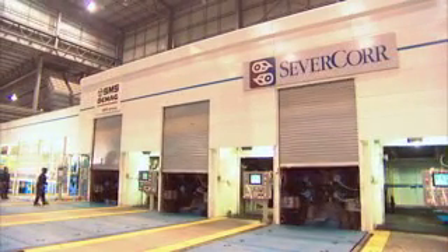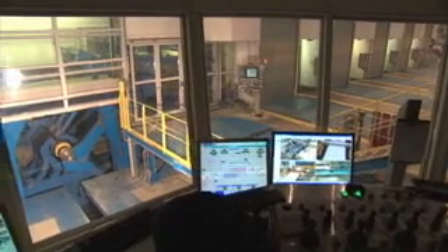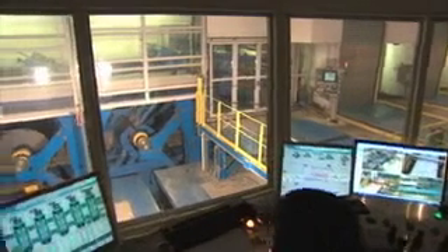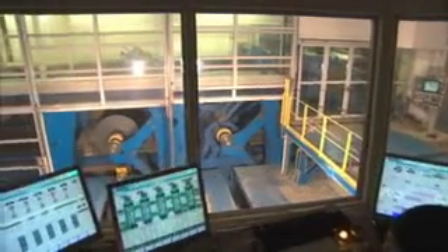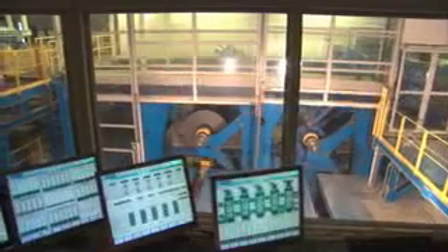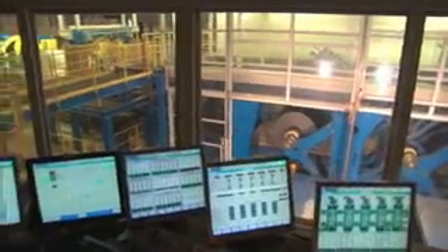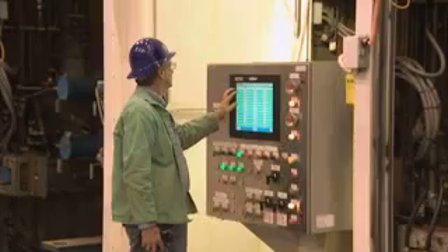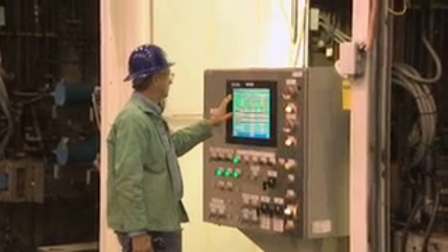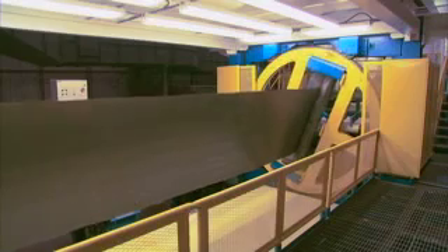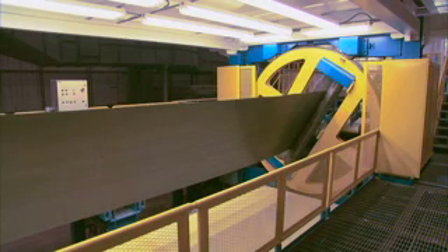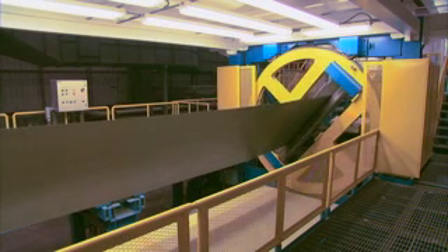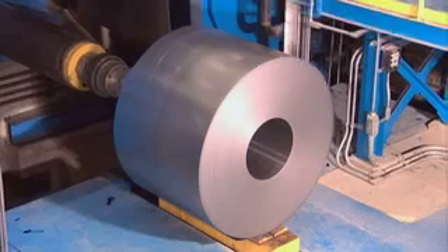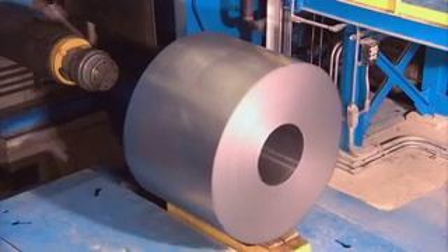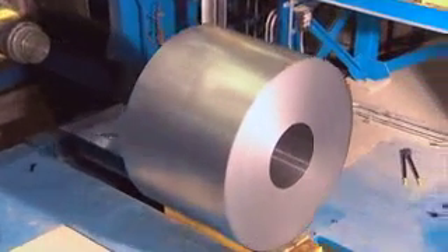Each cold mill rolling stand successively reduces the thickness, with gauges ranging from as heavy as an 0.75-inch gauge or the approximate thickness of a U.S. nickel coin to as light as an 0.14-inch gauge, again depending on the customer's order. The mill features a closed-loop gauge and shape control system and a 360-degree rotating inspection table to ensure the highest quality surface and shape. At this stage, the coil is a full hard cold roll product, primarily sold for roof decking.